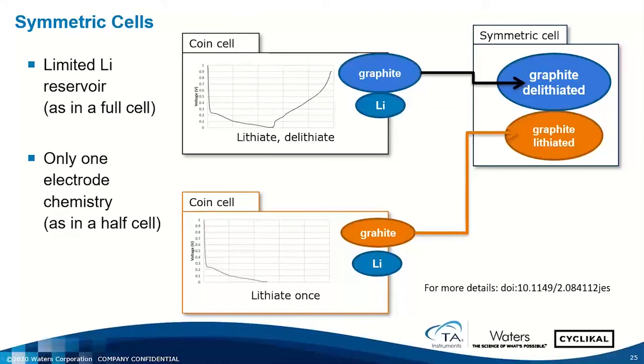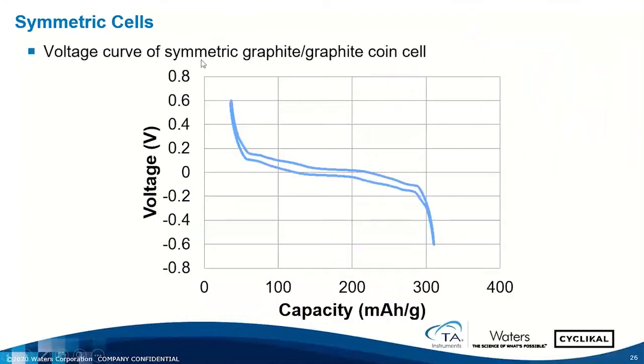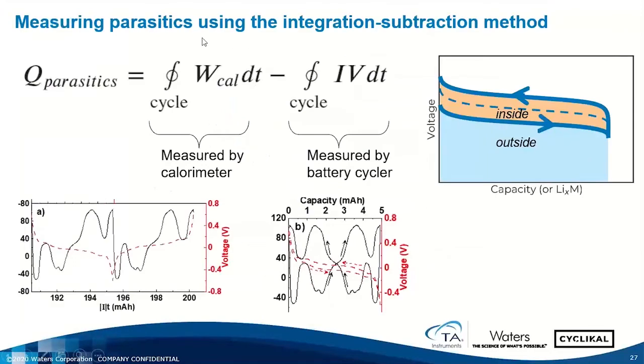And here's a voltage curve of a graphite symmetric cell. You can see the charge and discharge. And notice what looks to be an odd voltage range, but it can be appreciated because you're just rocking the voltages back and forth. All right, as Vincent mentioned, the technique we use is called the integration subtraction method. And quite simply, it's just integrating the thermal signal from the calorimeter over one full cycle and subtracting from that the area under the voltage curve. And doing that operation numerically gives one the parasitic thermal power.